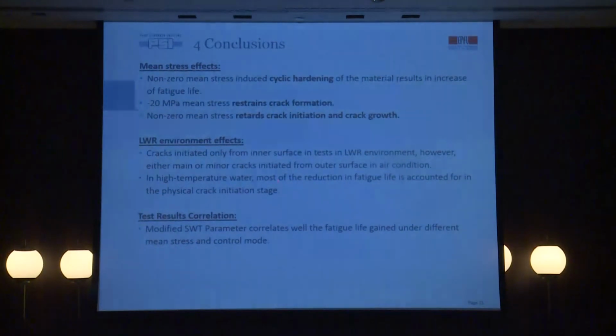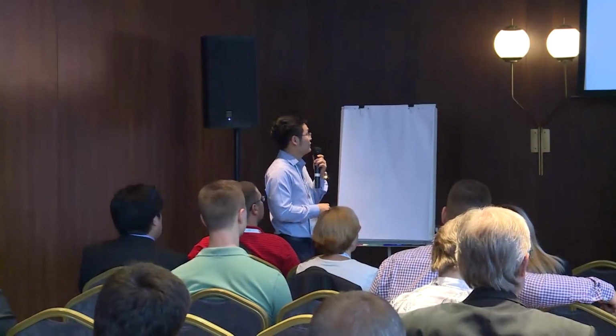In high temperature water, most of the reduction in fatigue life is accounted for in the physical crack initiation stage. And the modified SWT parameter correlates well the fatigue life gained under the different mean stress and the control mode.